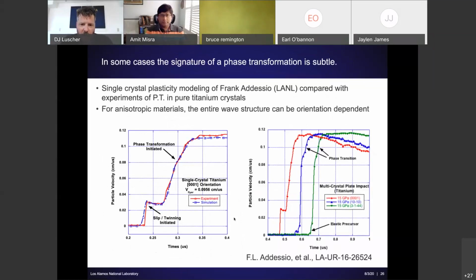The main points, so this is showing or emphasizing some modeling work done by Frank Addessio, also in the theoretical division at Los Alamos, where he was looking at comparing model of phase transformation in pure titanium crystals under plate impact loading with experimental measurements. And the main point I wanted to make is that we see a clear elastic precursor and then the initiation of slip and twinning at the HEL.